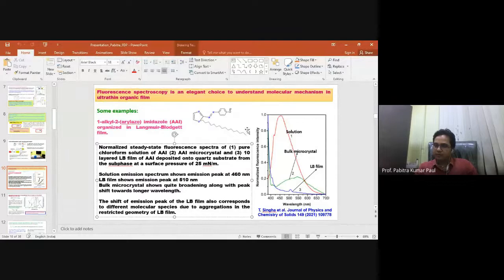We have assembled this molecule in LB film, and we found that this molecule can aggregate with an increase in the surface pressure. But the aggregation enhances the current when we measure the electrical signal. Also in the case of spectroscopic measurements, we have seen a huge change of the emission spectrum. This is the solution spectrum and the microcrystal spectrum. The solution emission spectrum shows the emission peak at 460 nanometer. The LB film shows emission at around 510 nanometer, so there is a shift of the emission spectrum. This shift of the emission of the LB film corresponds to different molecular species, and it is due to the aggregation in the restricted geometry of the LB film.